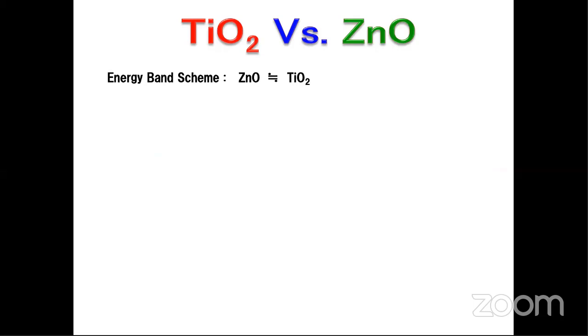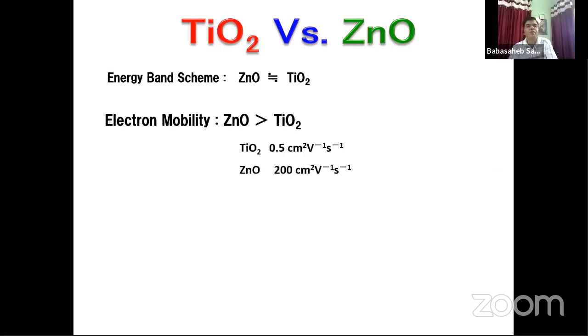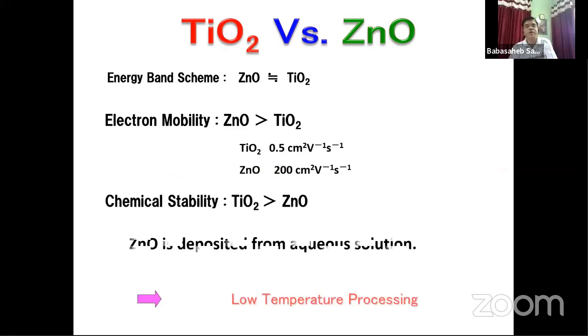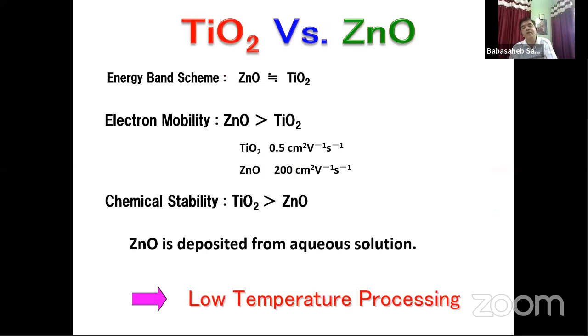So why have we chosen zinc oxide instead of TiO2? Because the energy band diagram is the same as that of TiO2, but the electron mobility is very high as compared to TiO2. But the chemical stability of zinc oxide is very low, and we have taken this as an advantage to synthesize zinc oxide at lower temperature as compared to TiO2, which is used at a very high temperature, that is 450 degrees Celsius. We have tried to reduce the temperature below 200 degrees Celsius, and we tried to get below 100 degrees Celsius but have not succeeded, but still we have achieved up to 200 degrees Celsius to have zinc oxide on the TCO layer.